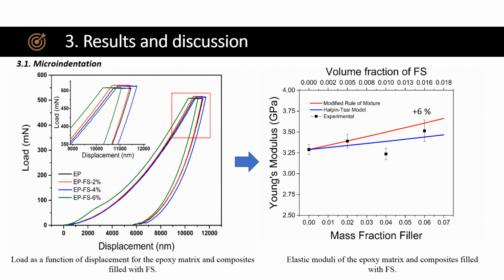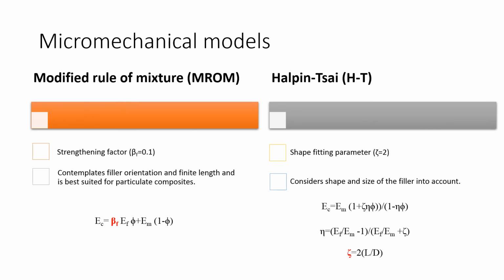It is observed that a maximum increase of 6% was obtained with the reinforcement mass percentage of 6%. These results are presented with the respective micromechanical models used, modified rule of mixture and Halpin-Tsai models. Micromechanical models are used to predict the final characteristics obtained through a composite based on the properties of its constituents. The first micromechanical model used was the modified rule of mixture. This model considers a strengthening factor, which contemplates filler orientation and finite length and is best suited for particle composites.